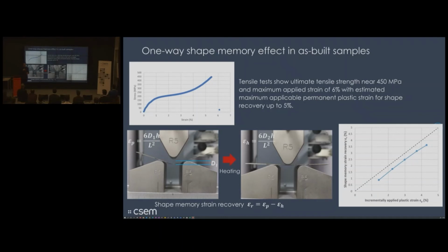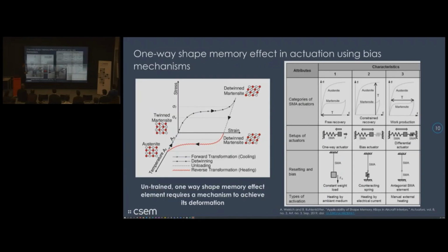I will make a small parenthesis here because we have demonstrated one-way shape memory effect already in as-built samples, and as it was mentioned, this is already useful to use in actuators. So just a small parenthesis on how we can use the one-way shape memory effect. We need something to apply strain in our part. With the heating, we always obtain the reverse effect, but we need to apply strain. And this strain can be applied by mostly three different setups for actuators.